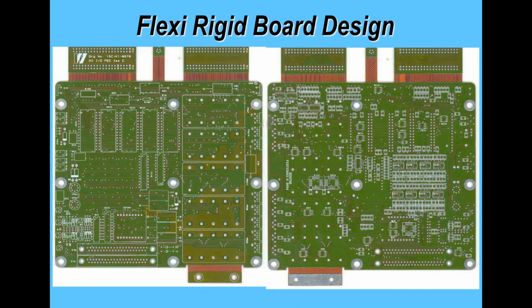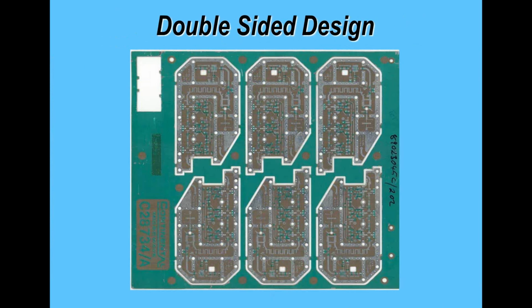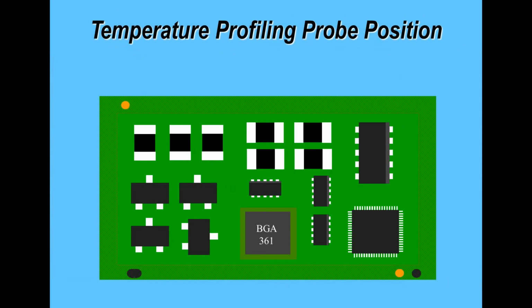So if we look at these couple of examples now, these are sort of typical boards that you or I might have to solder. So the key thing is obviously looking at the board and deciding where you're going to mount your thermocouples and the impact that certain areas of the board or certain components have on the soldering process. Here you see an example of RT Duroid, high frequency application material, with boards within a pallet area for processing, and these were actually for satellite communications.